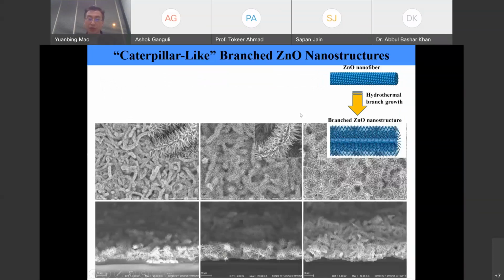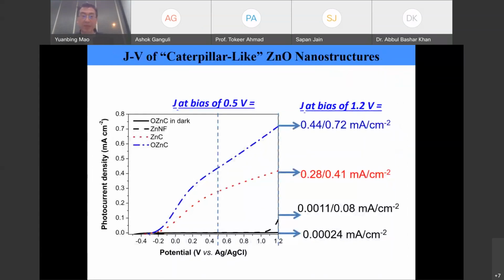Again, this slide shows that we can tune the diameter and the length of those branches. And you can see that they are pretty dense on the surface of the substrate. Then we did the same thing in terms of the photoelectrochemical performance. Since I already talked about similar things before, I will not go into the details. The samples we looked into: this is the optimized zinc oxide caterpillars, this is the zinc oxide nanofibers, and this is the not optimized zinc oxide caterpillars. You can see that the optimized zinc oxide caterpillars have a photocurrent density much higher than the other ones.